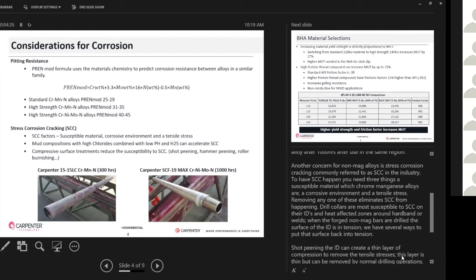When the forged non-mag bars are drilled, the surface of the ID becomes in tension. So we have a few ways to put that surface back into compression. Shot peening the ID can create a thin layer of compression to remove the tensile stresses. That layer is thin though, and it can be removed by normal drilling operations just from the erosion from mud flow, wear from MWD centralizers.